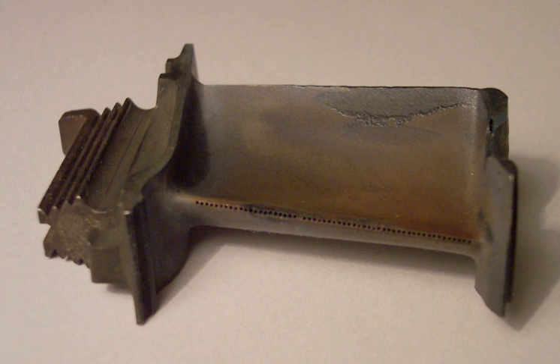Topic: plasma spraying. Of the various thermal spray methods, one of the more ideal and commonly used techniques for coating superalloys is plasma spraying. This is due to the versatility of usable coatings, and the high temperature performance of plasma sprayed coatings. Plasma spraying can accommodate a very wide range of materials, much more so than other techniques. As long as the difference between melting and decomposition temperatures is greater than 300 Kelvin, a material can be melted and applied as a coating via plasma spraying.